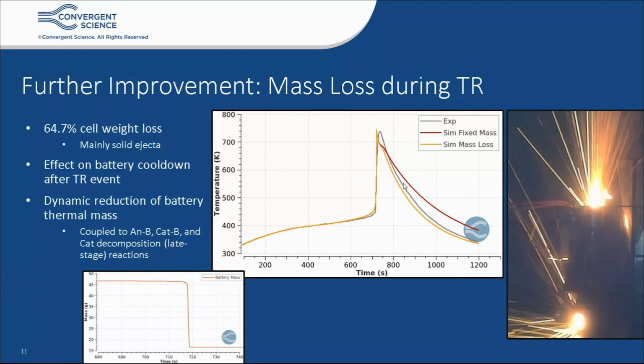And it's also important to consider when you do module level simulations, because a battery with lower thermal mass has lower energy to transfer through conduction to adjacent cells. And this is something you want to include in your simulation framework, and also include dynamic battery thermal mass reduction during the thermal runaway process. In order to make the mass reduction more predictive, and having experiments to guide us, we coupled the mass loss equation to the late stage reactions for binders and the cathode decomposition process. So as you can see here, there's a dynamic reduction of battery mass during the simulation. And now, as you can see with the curve in orange, we get the correct cool down trend. And now we have a much more optimized thermal runaway behavior in our simulations.